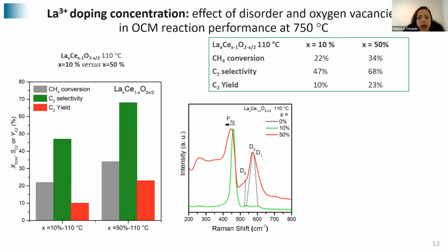As we can see here, there is a difference in the amount of oxygen vacancies that was mentioned in the beginning. These oxygen vacancies are really important in the OCM reaction. As you can see here, this is the performance of the sample with 50% of lanthanum, the spectrum in red. We have a higher amount of defects. So we can see here the conversion and the selectivity are much higher than the sample with less lanthanum. So this really affected the reaction.